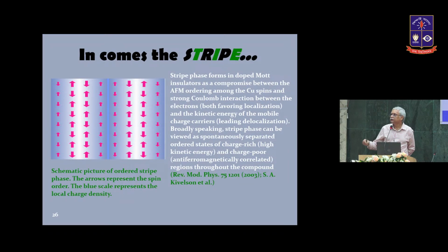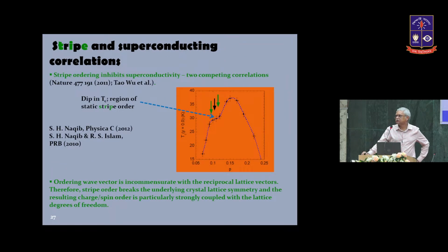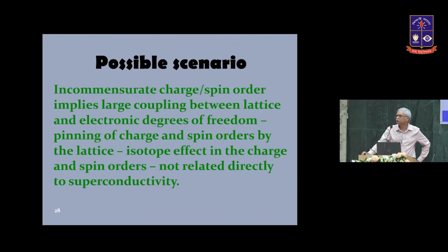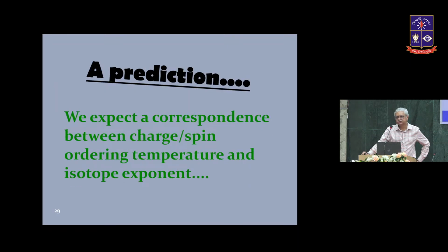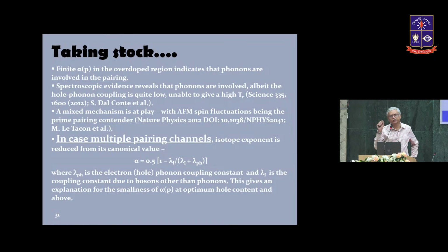Okay, so if we summarize the results that I have shown till now, since there is an isotope effect in the overdoped region, though the isotope exponent is very small, it is still there. I must say that in the overdoped region of the electronic phase diagram, there is no sign of spin or charge density order. The spin and charge density order only exist in the underdoped region. So in the overdoped region, we get a very small isotope effect.